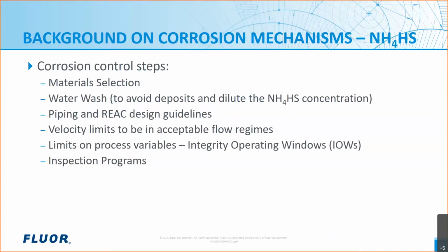So the water wash, remember we saw the water being injected upstream of the reactor effluent air cooler in those PFDs. So water wash is a key step for preventing this corrosion. It both avoids deposits and it dilutes the ammonium bisulfide concentration. And there's many guidelines to achieve a proper water wash. You have to have the right quality of water, can't have contamination with oxygen or cyanides. It needs to be injected with spray nozzles to make sure it has very good distribution.